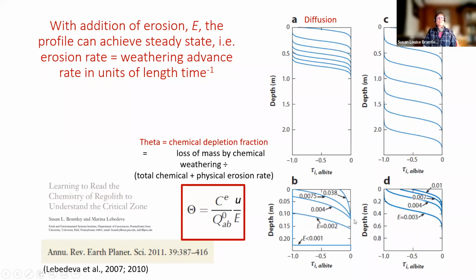Well, then you can get these steady state models, and you still see a reaction front. So here's a reaction front. This is the case for a very, very low erosion rate. If you have a very high erosion rate, you can actually end up with albite that makes it to the surface. So just to recap what I was saying, 0 is parent composition, -1 means 100%, all the albite is gone. So a reaction front that looks like this, some of the albite is making it to the land surface. And so basically what we're saying is with very slow erosion rates, the albite goes through here so slowly that it dissolves away before it reaches the land surface.